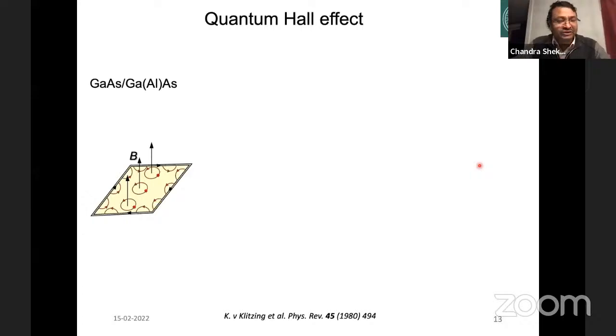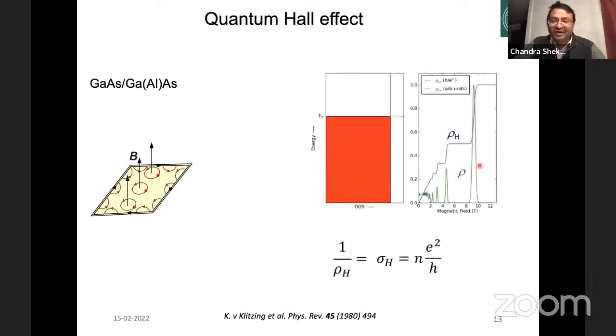We are able to synthesize a two-dimensional device, and when we apply a magnetic field and measure the same Hall voltage, what do we see? We see a Hall voltage. This material is non-magnetic. In principle, if this material were three-dimensional, it should behave linearly like the first one. But this material is two-dimensional, so it is not behaving linearly. It behaves like a stair.